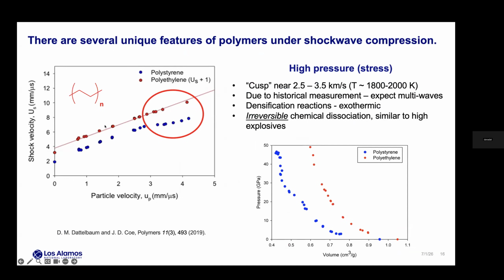So again, I have polyethylene in red, polystyrene in blue, and I think my chemical structure for polystyrene disappeared. I was thinking maybe it would come back. Anyway, polystyrene has an appended benzene ring, or phenyl ring. And what you can see is that there's this large cusp in the Hugoniot. And again, that was proposed to be related to dissociation.